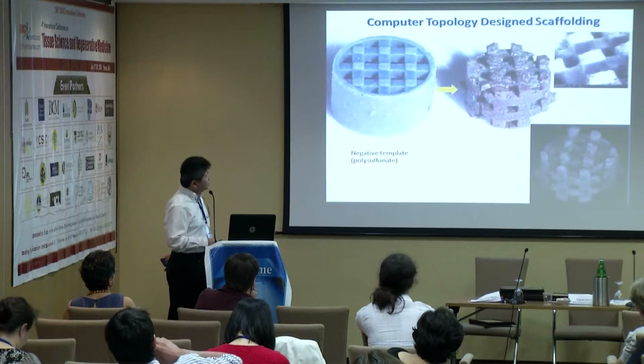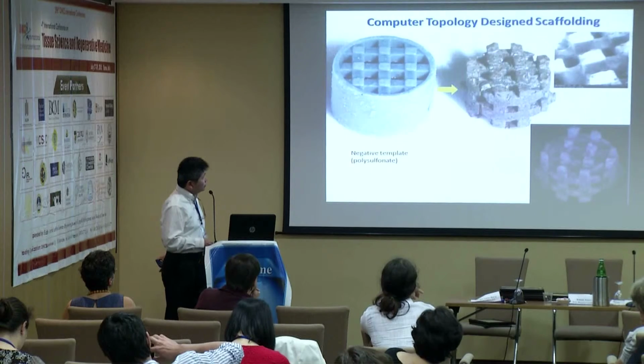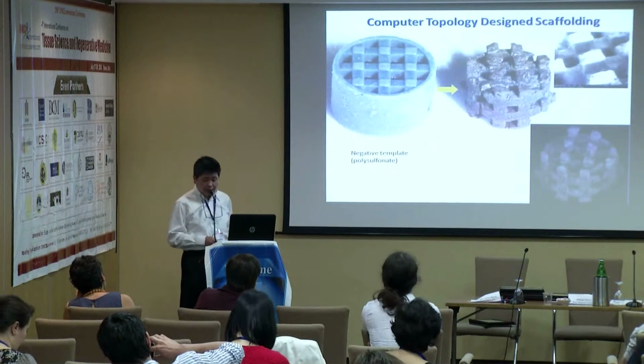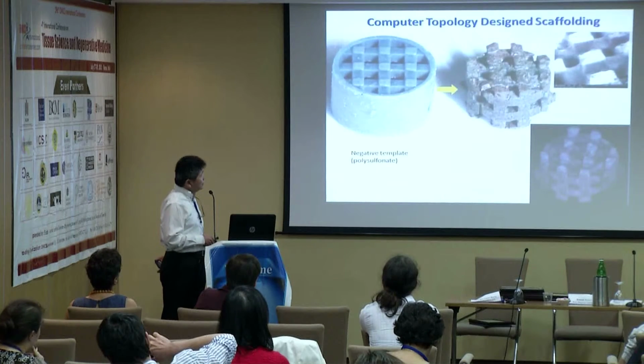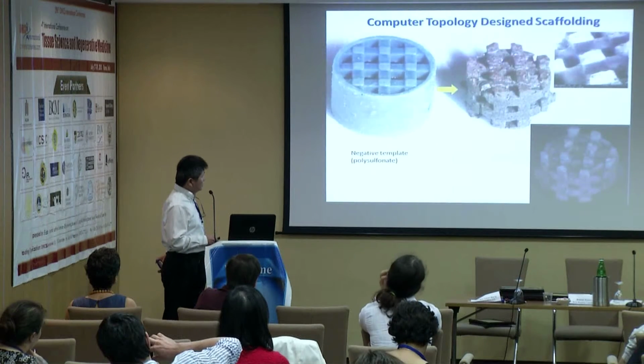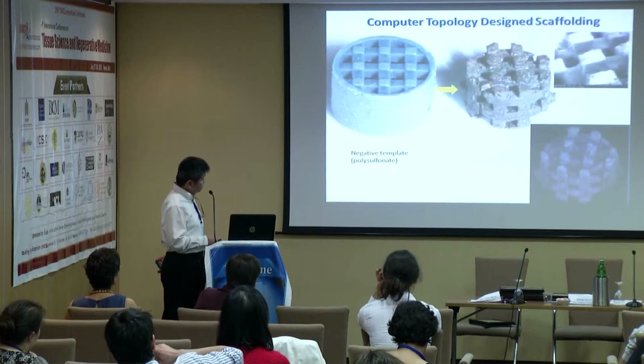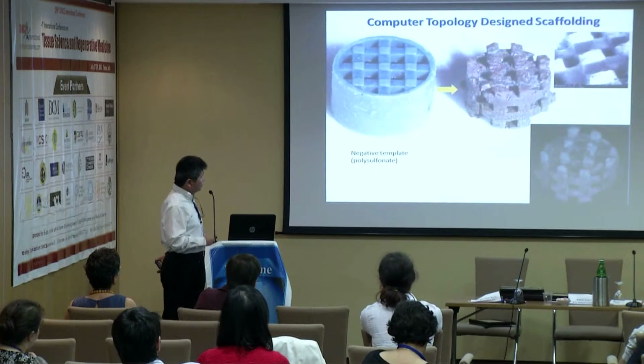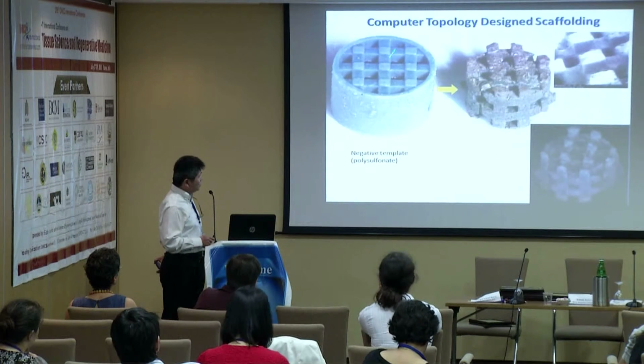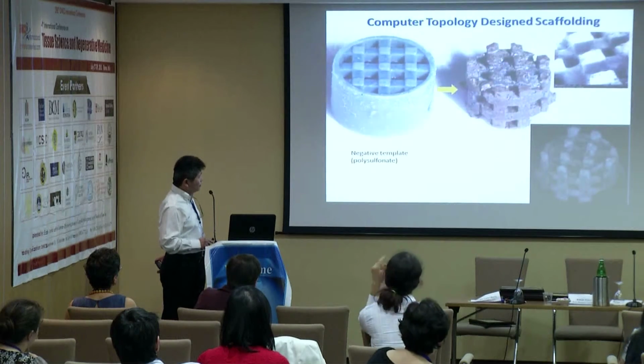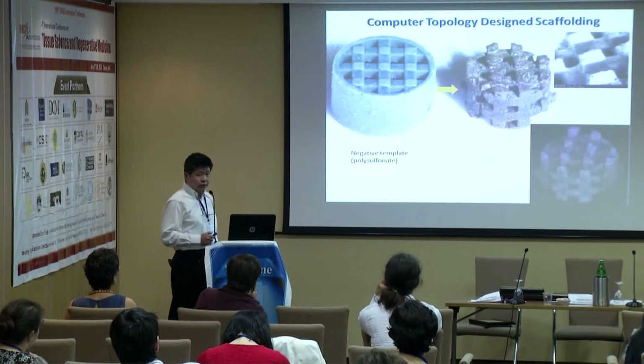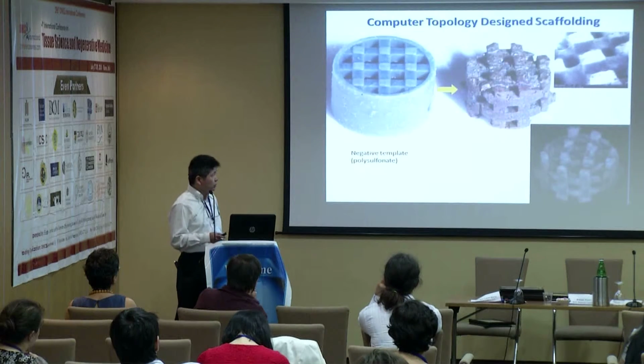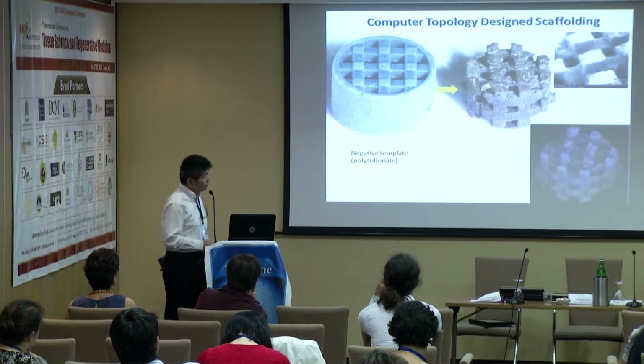And besides that, the system also allows us to do computer design, to design the scaffolding. What we did now is use the indirect scaffolding method, which means we're using polycarbonate to design a negative mold, and then we infiltrate our composite fluid before it's set, and then quickly remove this polycarbonate using an acetone solution, and within about 3 minutes it would remove the material. So we can start to design different types of geometries and prostheses.